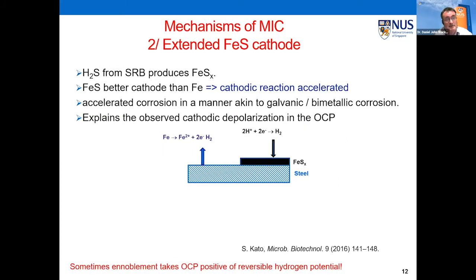The next mechanism, which I used to like until more recently, is the idea of an extended iron sulfide cathode. The H2S produces iron sulfide. Some iron sulfides are quite conductive and can be a better cathode for hydrogen evolution than iron itself. Essentially we've got galvanic corrosion: this is your iron sulfide, it's your cathode, and iron corrodes over there on the iron.